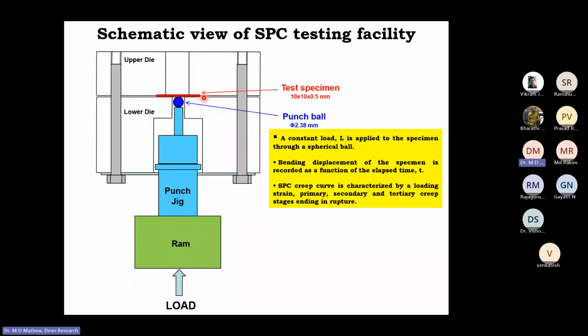So this is the sample. This is your ball, the ceramic ball, and you have the ram here. With the ram, you are loading the ball, and once the ball is loaded, it is loading the sample also. So a constant load L is applied to the specimen through the spherical ball, and the bending displacement that occurs is recorded as a function of time. So once you have the time data and the deflection data, you can make a plot of deflection versus time, and that is what is called the small punch creep curve.